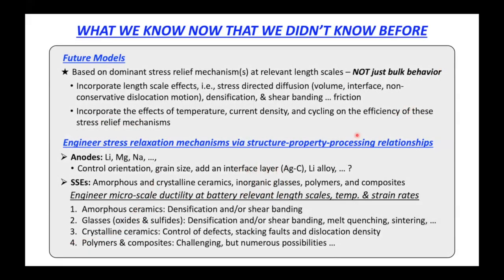So just in closing here, there are a lot of takeaways from all of this, but I think the most important message in relation to generating future models to try to address these issues is that you really have to think about the mechanical properties of these materials at relevant length scales. And those relevant length scales are going to be the length scales of defects at the interface, right? The bulk properties are clearly important, but those properties alone are not going to allow you to solve this problem, right? So we need length scale effects, and we need to think about how those length scale effects are going to be impacted by a number of operating conditions. So temperature, current density, cycling, right?